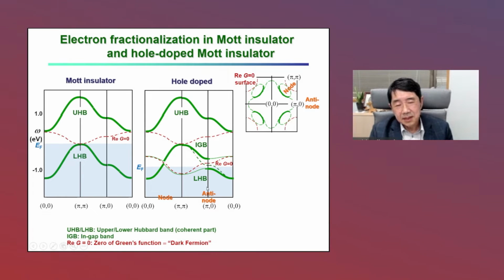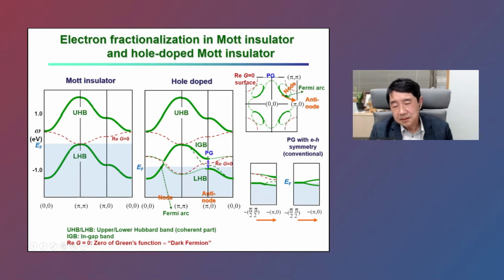And this is a cartoon picture of this situation. The Mott insulator's lower Hubbard band is split by hole doping and creates a pseudogap, which is quite large and asymmetric, which is quite different from the more conventional view that the pseudogap is electron-hole symmetric, but actually it is quite asymmetric. This is not a proposal, but the result of the numerical calculation. And so the Fermi arc can also be well described.